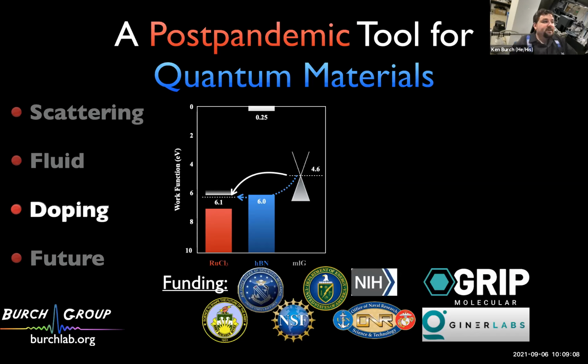What that means is that this ruthenium chloride essentially acts like an acceptor, in the old school semiconductor language, which is to say that if you put graphene on it, it will just soak charge out of graphene. So you can actually get to a Fermi level of about 600 meV in the graphene just by placing it directly on ruthenium chloride. What's more, because this charge is so enormous and comes from this charge transfer, it's also very short in length scale, as I will show you.